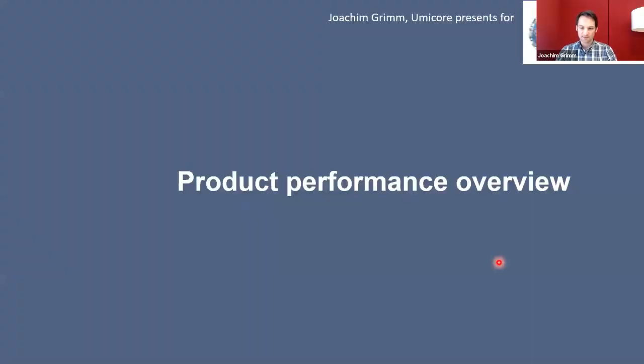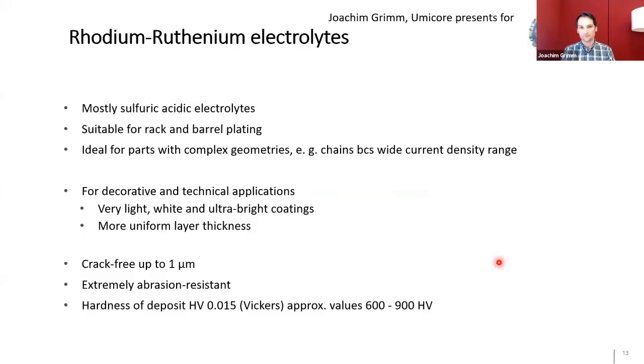So I will show you a little bit of product overview about this precious metal alloy plating, about this rhodium-ruthenium and the other alloy platings. So most of these platings are sulfuric acid based, as they come from the pure rhodium electrolyte. So the basic is usually sulfuric acid. And so far I can see, the available products on the market are suitable in rack and barrel plating. So they give the same opportunities like with pure rhodium. And especially the rhodium-ruthenium electrolytes seem to have a really good throwing power. So you can work in a wide current density range. So it doesn't matter if you work with low or high current or power, complex geometries like chains are really covered inside and outside, even and similar.